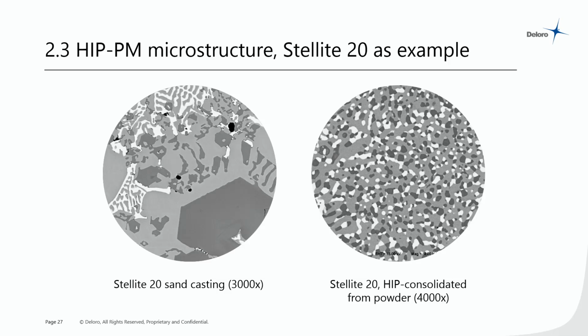But if you look at the shape of those carbides, and if you imagine a crack potentially traveling through this microstructure, it's not a very ductile microstructure. It's not a very tough microstructure. It's extremely wear resistant, but it is not ductile.